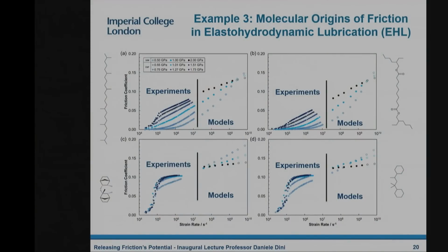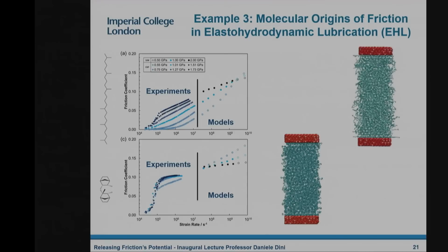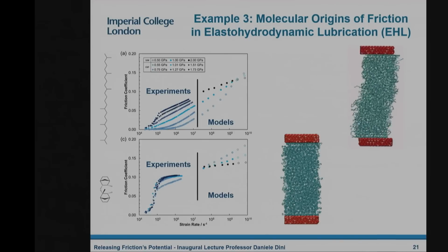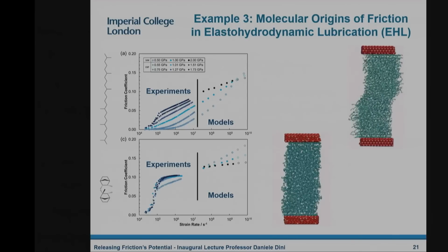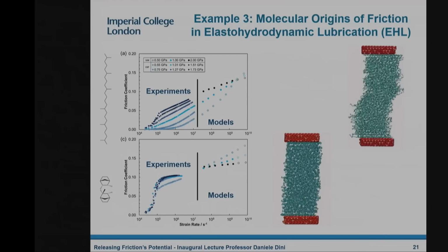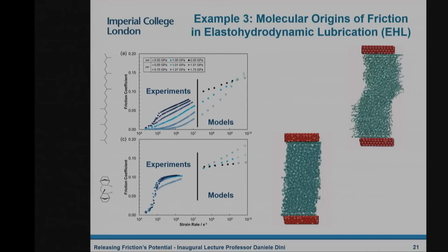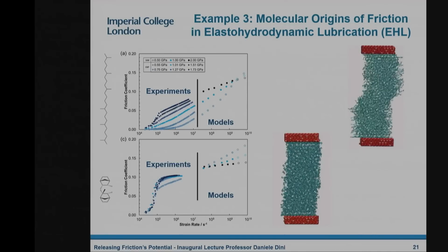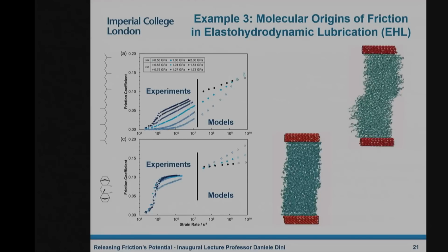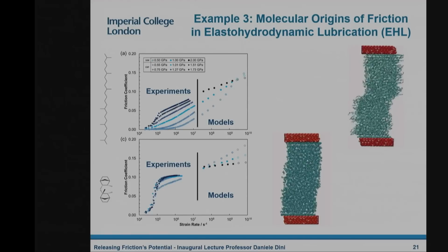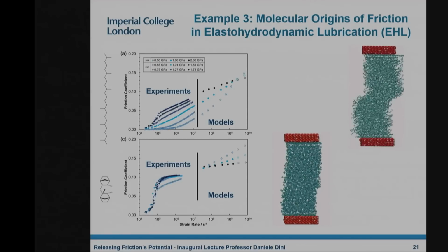And this is shown to be a function of what happens to these molecules when they are sheared. And in fact, as I said, the simulations are the key. If you look at this simulation, you'll find that the structure of this fluid, when it's confined between these two walls, is responsible for the different behavior. And in fact, for things that are much bulkier, this is all due to shear localization. And this shear localization happens much earlier for this type of molecules, which are bulkier, than for this type of molecules that tend to shear more easily.